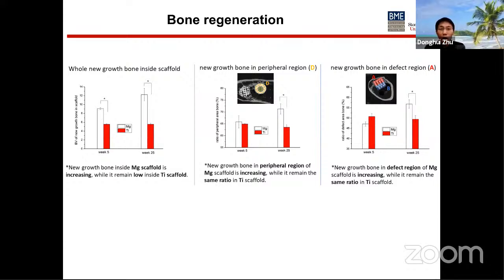Now we look at the overall bone regeneration. The bone volume is significantly higher for magnesium than titanium, indicating magnesium is pro-bone regeneration compared to titanium. For titanium, there's new grown bone inside the implant, distributed quite homogeneously. For the magnesium scaffold, the new grown bone seems more preferred at the peripheral region, closer to the natural bone structure.